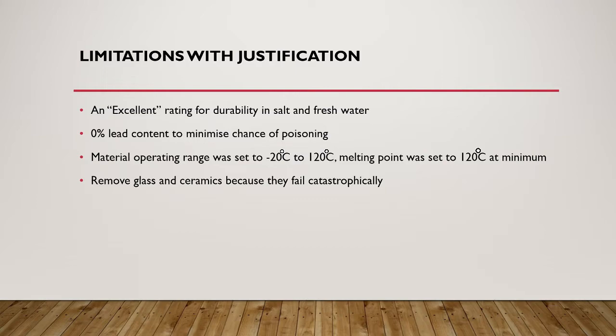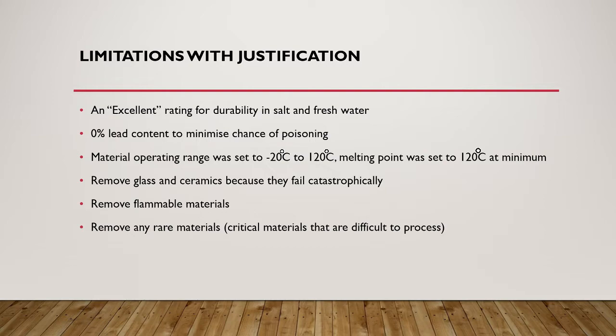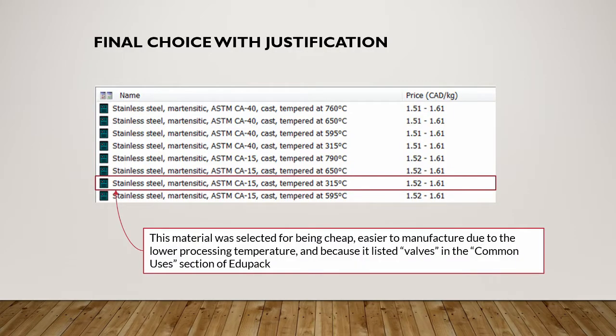We want the valve to leak before exploding. We remove flammable materials and rare materials to minimize manufacturing costs, and we also remove any non-castable materials because castable steels are much easier to manufacture. So we ended up picking a CA-15 cast steel tempered at 315 degrees Celsius.